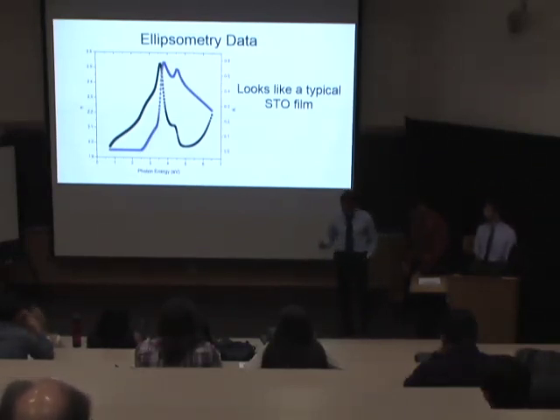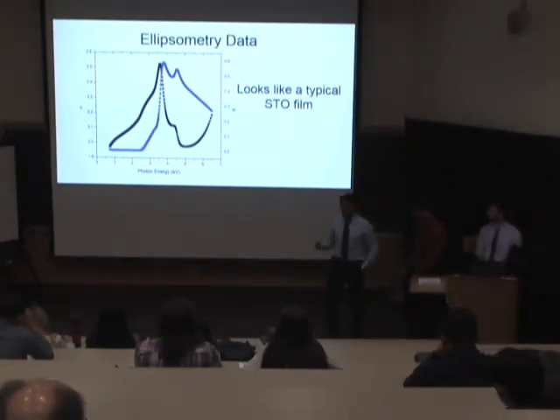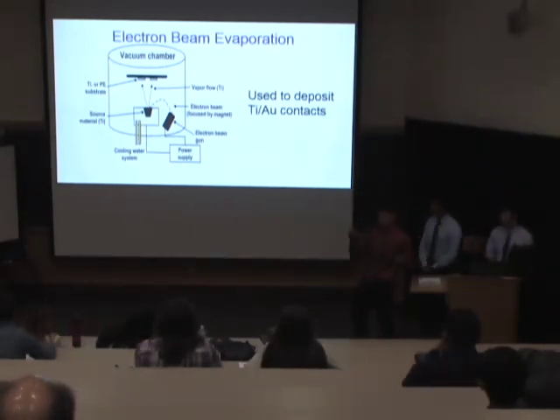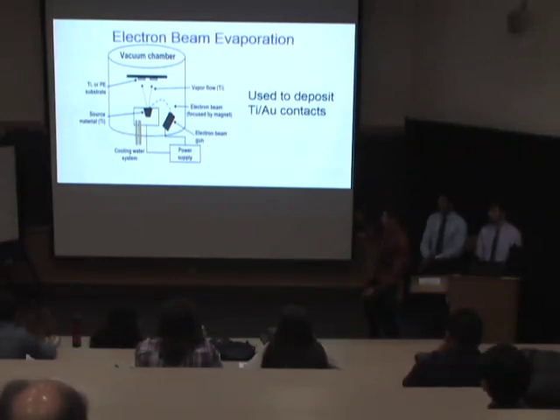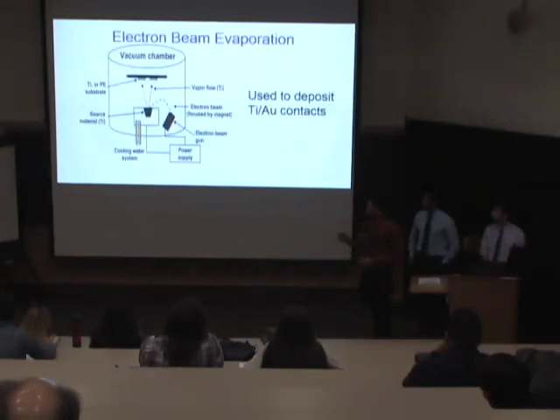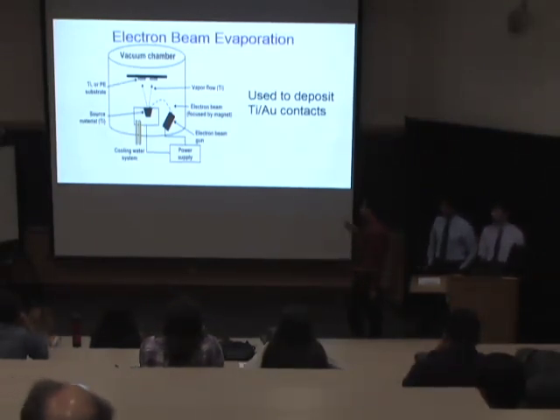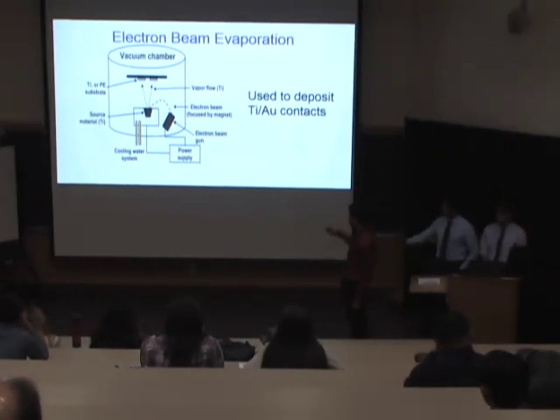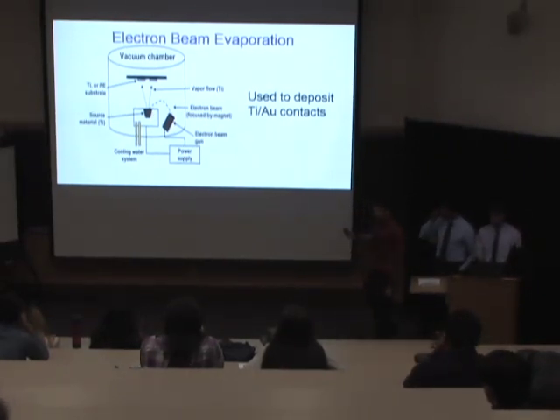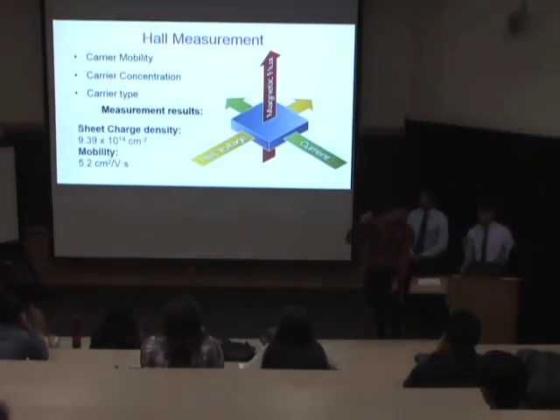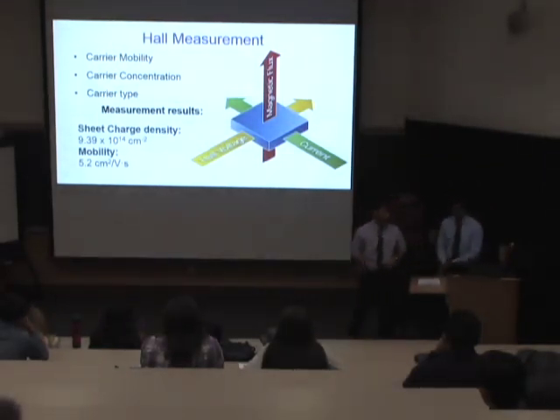After we have found our ellipsometry data, it's important that we look for electrical data as well. The first process of getting the electric conductivity of the thin film is to get 4 contacts placed on the thin film. So we use titanium and gold. How we do this is we go to the electron beam evaporation, which is located in the nanofab. We vaporize the titanium and gold, which is located in this crucible, with this electron beam gun. It's important to have these contacts established for when we take our Hall measurements.